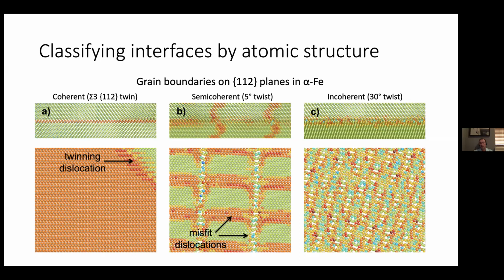And here on the bottom, if you look into the plane of the boundary, so perpendicular to the plane, you can see that there's now a very distinct structure. You've got these patches here of very good atom-to-atom matching. We would call those coherent patches. And those coherent patches are separated by lines of misfit. Turns out that you can actually describe these lines of misfit separating the coherent patches as misfit dislocations. So I think many of you may be familiar with dislocations from studies on single crystals, plasticity, things like that. You can actually see these misfit dislocations forming at low angle semicoherent boundaries, such as this one.